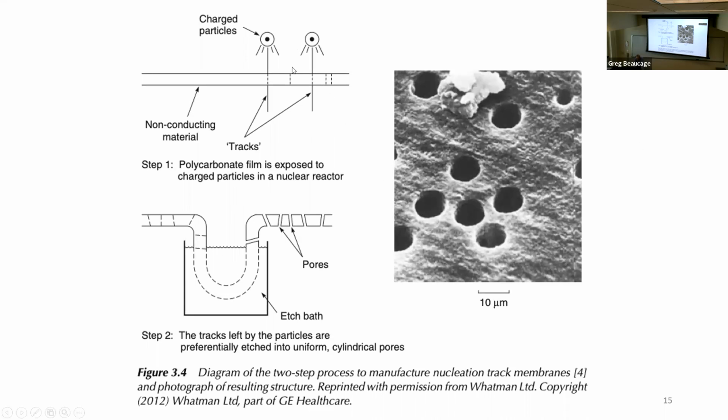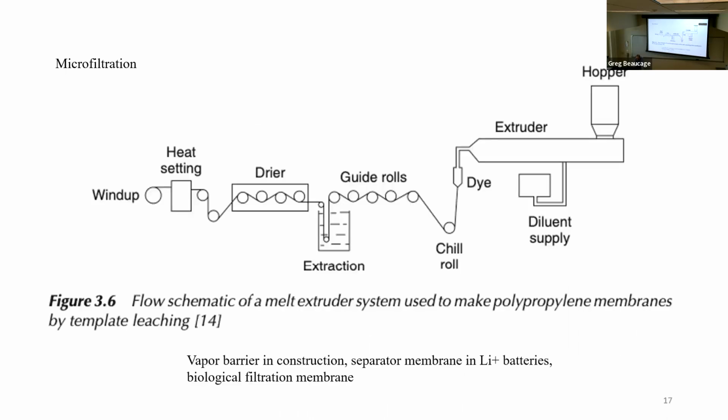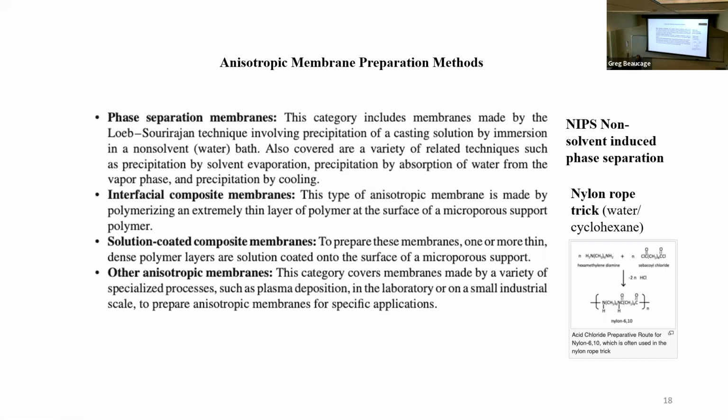micropore films with radiation. You can just blast it with ions, basically, and blow holes in the membranes. And we looked through this before, like drawing out polypropylene, you get pores. If you put starch into polypropylene and disperse it, then you can wash it out and make porous polypropylene. If you want, it can act as a kind of filtration barrier.